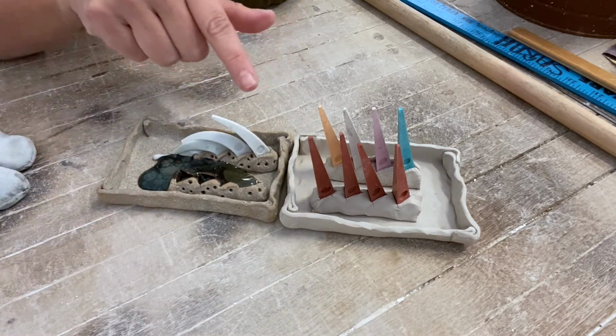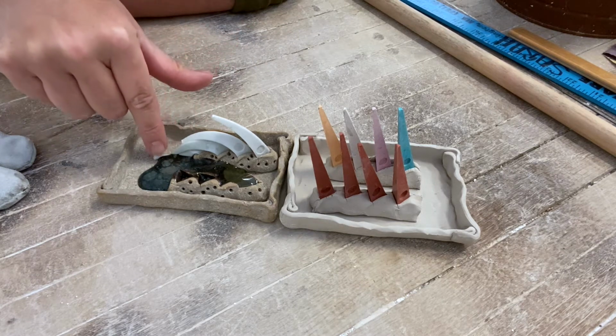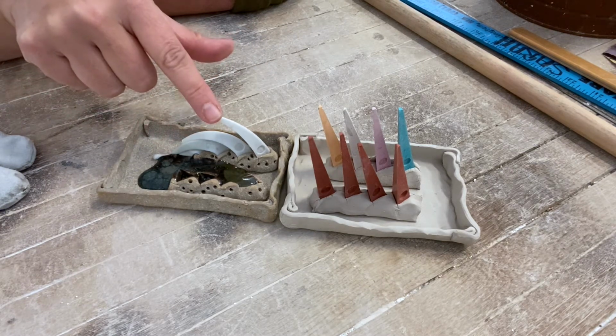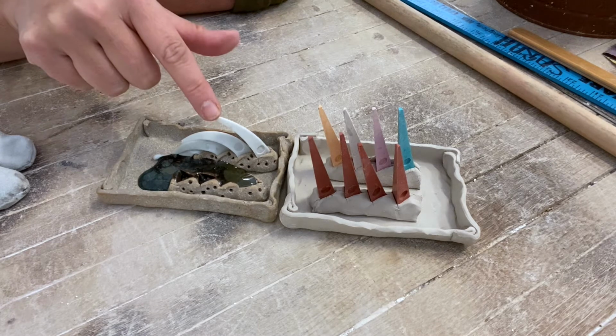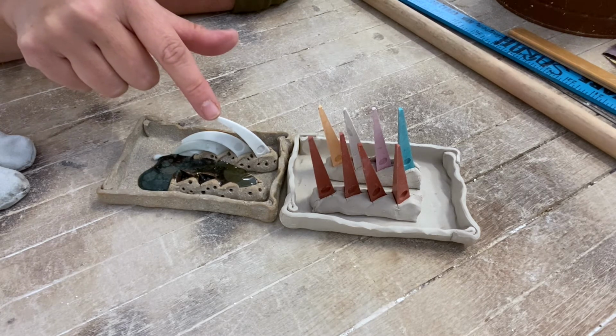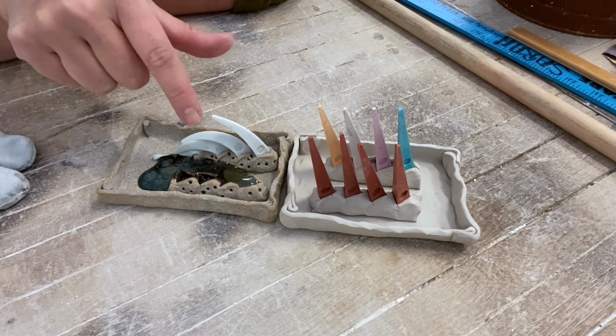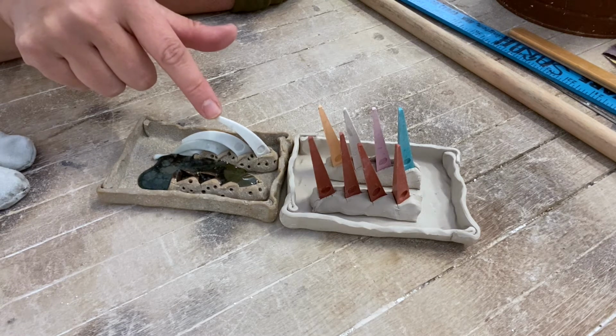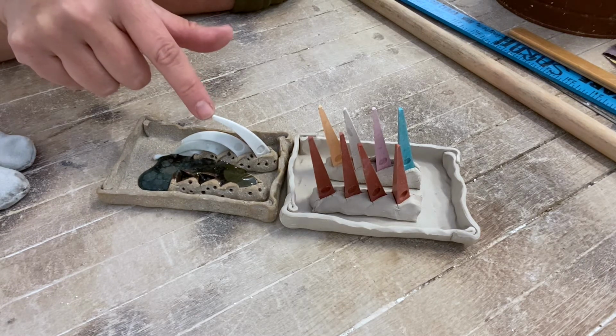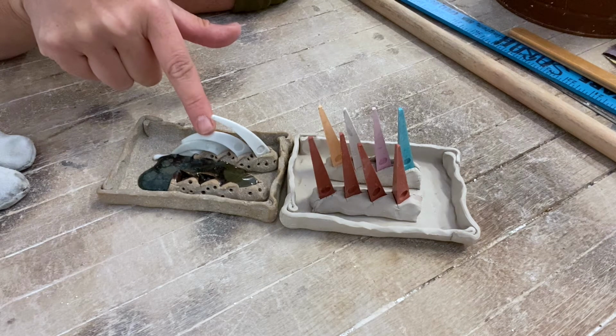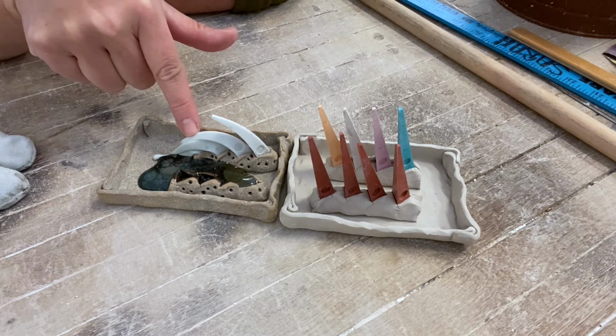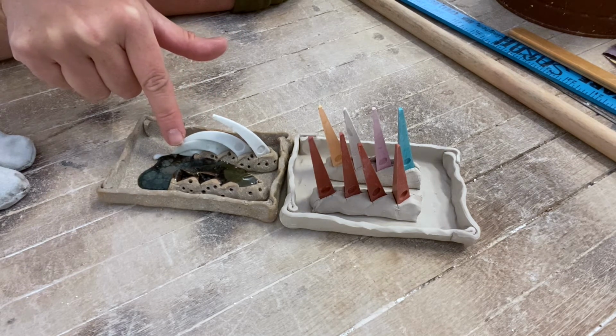The cones that are here for the later part of the firing are going to tell us when we're achieving our target temperature, which would be around 2300 degrees Fahrenheit. So this cone 10 cone I can see is beginning to get soft, whereas the 9 cone has already bent all the way over and hit the next cone.